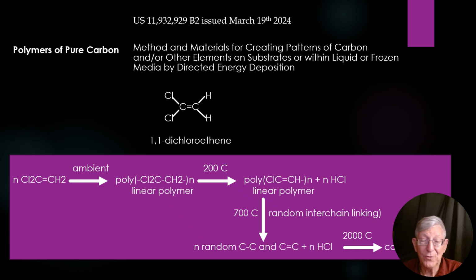Now it turns out if you want to take this material and heat it up like 2,000 degrees, which is like the type of temperature that the physicists like to work in, it's also a temperature that is used to make carbon fiber. Carbon fiber is made from polyacrylonitrile, but carbon fiber has to go through a couple of steps, an oxidation step and other types of steps, which make it kind of messy. But this stuff, once the hydrochloric acid is out, you end up with a very pure carbon. But if you heat that up, then you can make something that looks like a carbon fiber out of it. But that has to go up to like 2,000, 3,000 degrees.